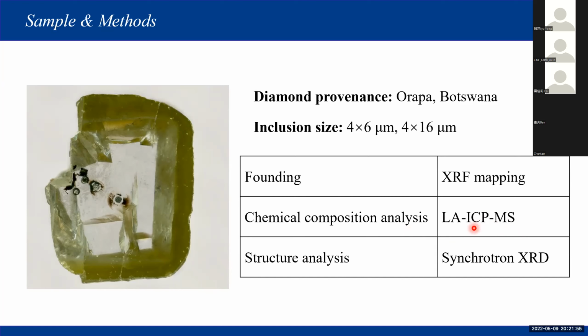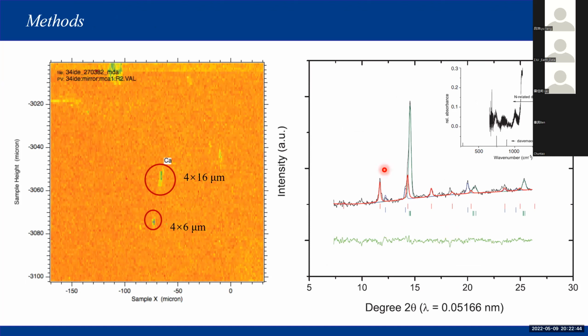But in this part, LA-ICP-MS, we know they use a bin size of 100 by 100 micron, and we can know the inclusion size is smaller than the bin size. So the authors identify the inclusion minerals by mass balance. The composition of the individual mineral was obtained from the composition of the bulk inclusions. This is about the chemical composition analysis. Then let's take a look at these three methods.